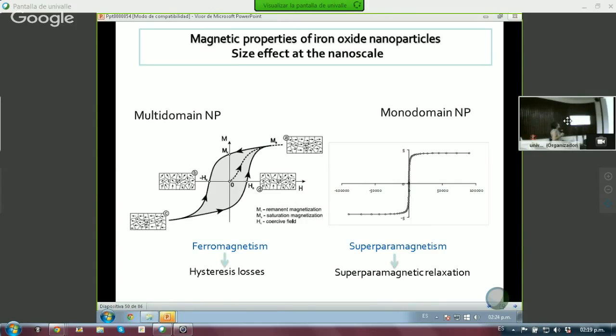You can buy it. And this is a small reminder of the difference between the magnetic properties of these iron oxide nanoparticles. So here we have the multi-domain, and as you can remember, we have the hysteresis loops, and different properties. And on the monodomain nanoparticle, what I would like you to remember is this very steep curve around 0. You see how the slope is very strong, and this is the indication of the magnetic susceptibility of these nanoparticles, which will be very useful later on when we put them in a magnetic field.